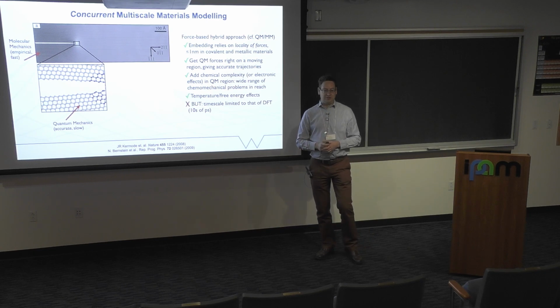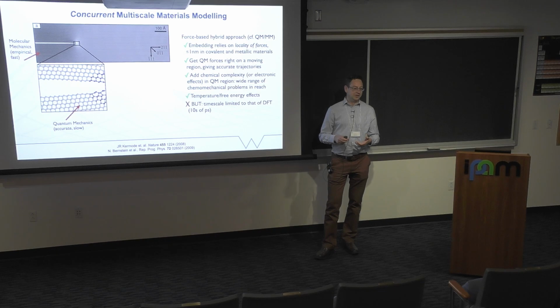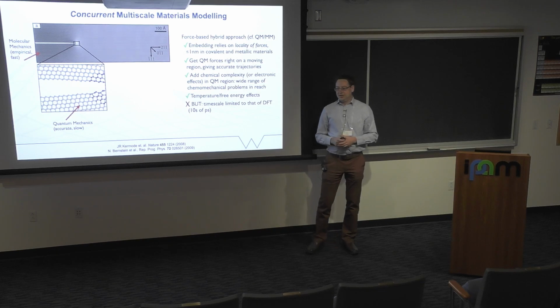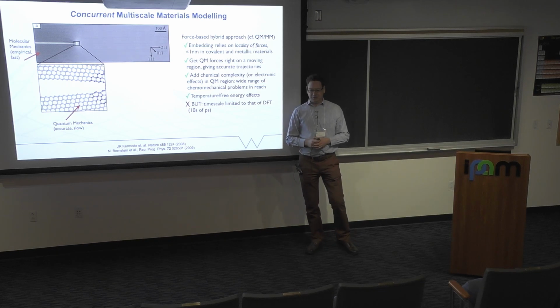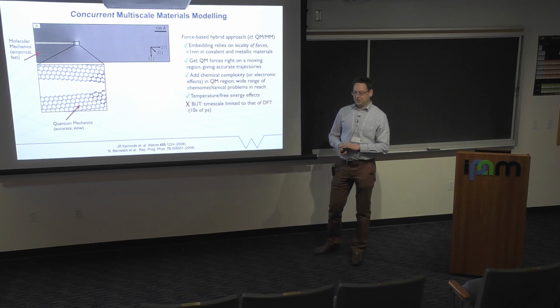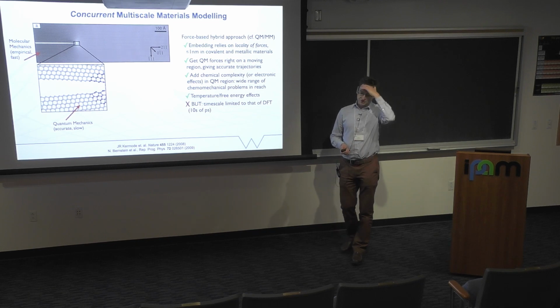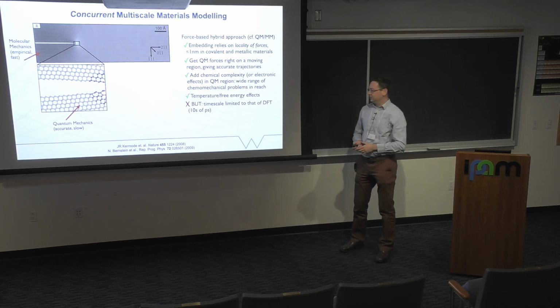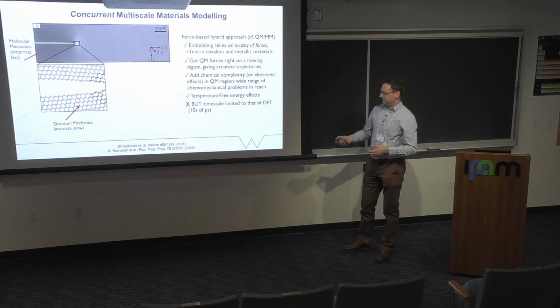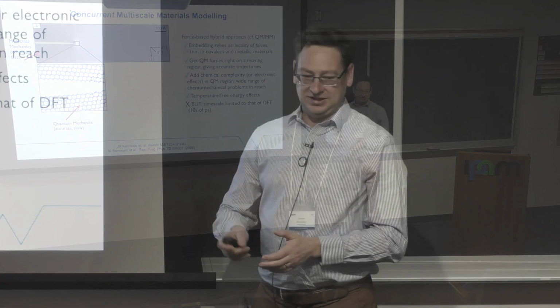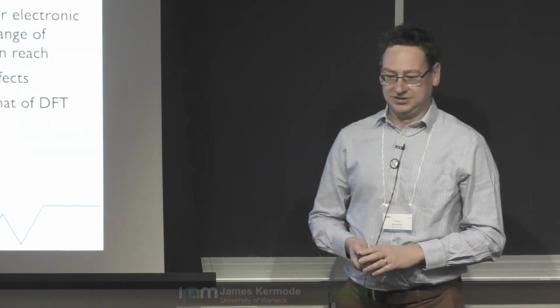We can put as much chemical complexity as we like into that near tip region without having to do any reparameterization, because it's a first principles ab initio method, so we can look at things like stress corrosion, where there are chemically aggressive species, water, oxygen, etc. around, or we can put impurities in without having to refit models and take advantage of the transferability that's intrinsic to the quantum mechanical method. However, we're a bit stuck in terms of timescale. The clock is set by the cost of doing DFT calculations at every step.